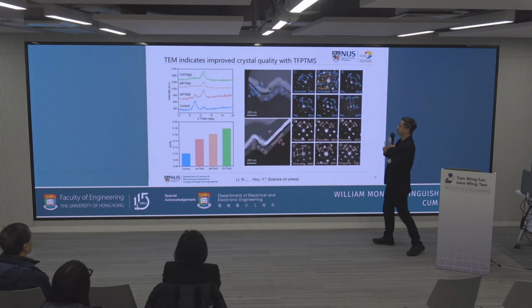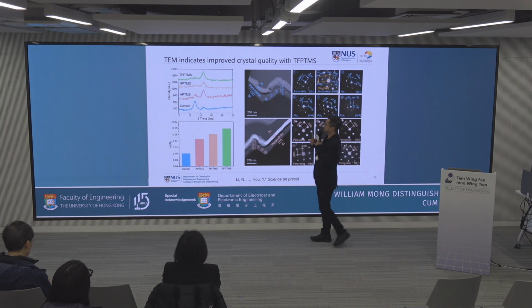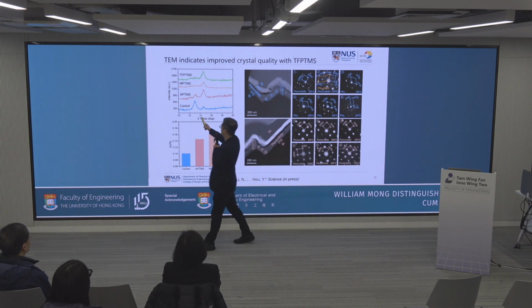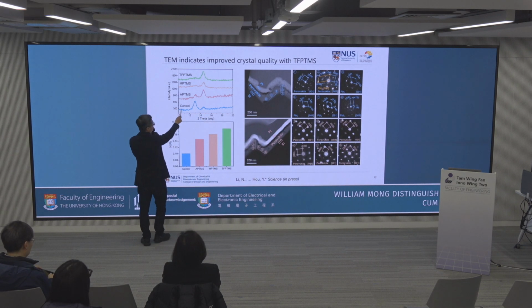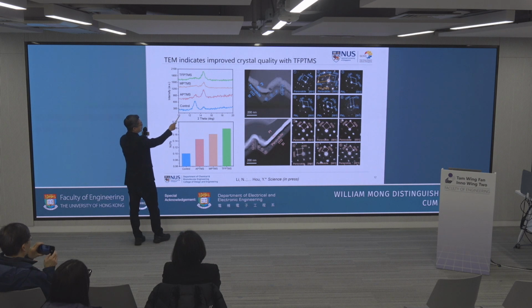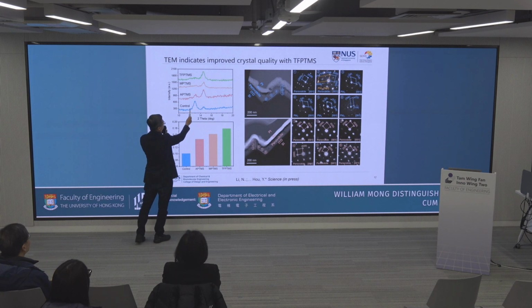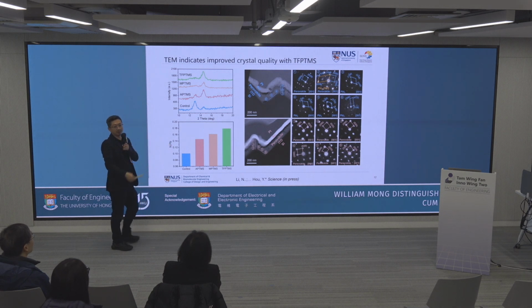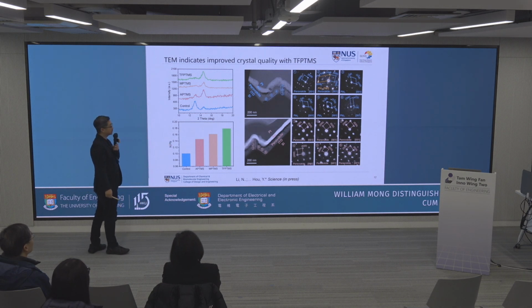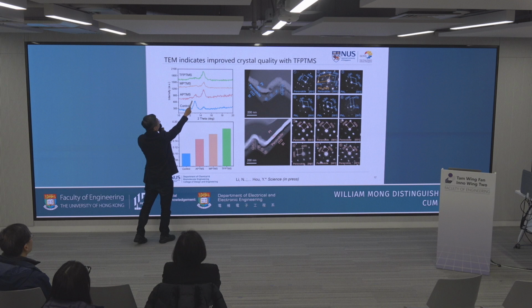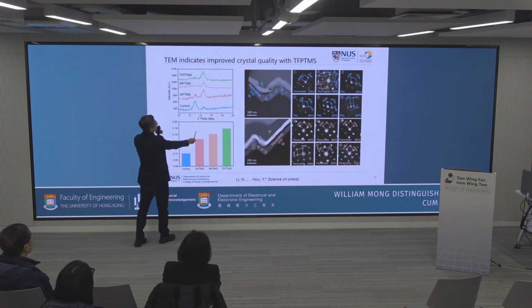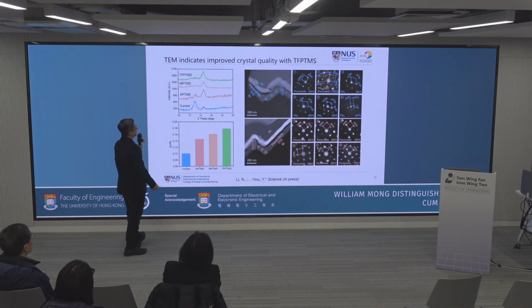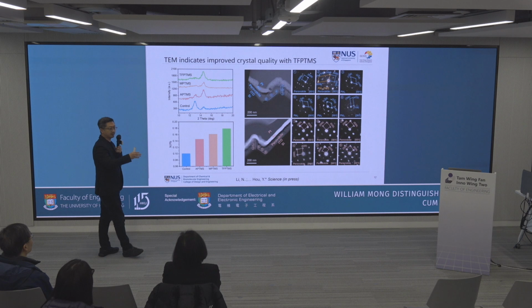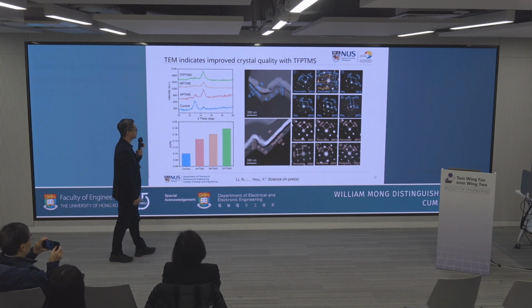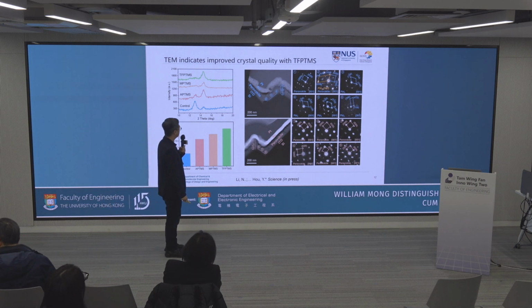So with the balanced adsorption using this molecule, you can see this evaporation at the very beginning, and the controlled samples without any modification of the surface. You can see at the very beginning of the perovskite evaporation, all you see is a lot of this inorganic lead iodide component. You don't have the perovskite form. So with the treatment, you can see more perovskite film peak formation, and so it strongly indicates we can balance the inorganic organic component on the substrate to form a high quality perovskite.